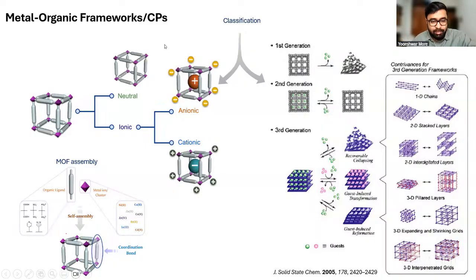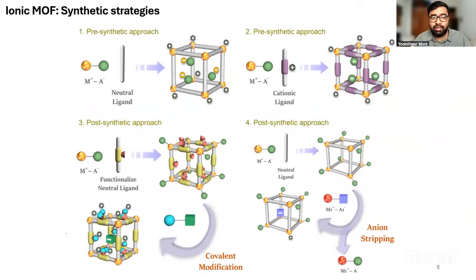And here, on the left side of the slide, the ionic MOFs have been shown. Why ionic MOF? Because it is very necessary to have an ionic MOF to have ion exchange. Since the uranium is a cation, to remove the uranium, we need to have an anionic framework or anionic assembly. And this anionic assembly is nothing but the anionic MOF. And generating such an ionic MOF is another challenge. So we will see how to generate these MOFs.